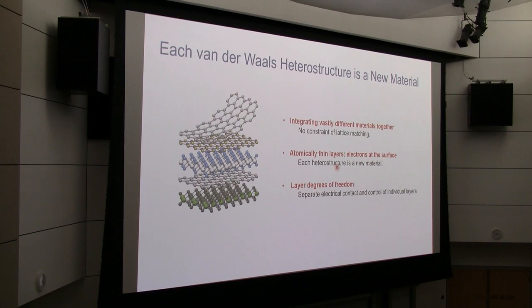The other very interesting and important aspect is these layers can be atomically thin. What that means is all the electrons are sitting on the interface. When you put two layers together, an electron in one layer will see the other layer very strongly. As a result, the heterostructure behaves very differently from an isolated monolayer. So each heterostructure is a new quantum material that doesn't exist in nature. And you can see there can be a lot of different combinations that you can make once you stack two layers or multiple layers together.